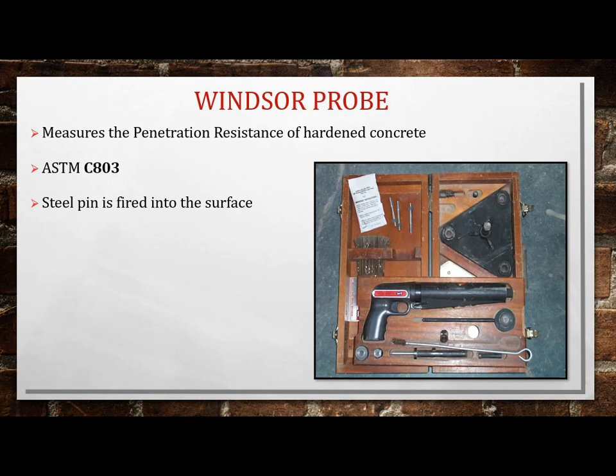There's a way you can test three of them and take an average of the three. And so with the Windsor probe and the rebound hammer, the accuracy is like plus or minus 15%. You can't guarantee what it is, but it's pretty close. But like the rebound hammer, it's a very good tool to compare elements. So if you've got 30 columns, you can test all 30 of them, and you can determine which one's weaker than the other.